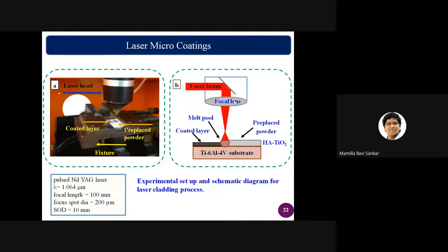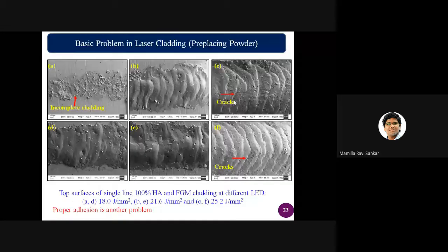Then what we have done, as a mechanical engineer with laser technology, is that one can use lasers for pre-placement technique based coating technologies. However, the drawback is that it is not good. The coatings are not up to the mark, because for internal fixation devices for orthopedic applications, the coatings metallurgically as well as metrologically are not up to the mark. At the same time, surface integrity is also not good, because you always find some cracks because of the interaction between the metal and the ceramic.